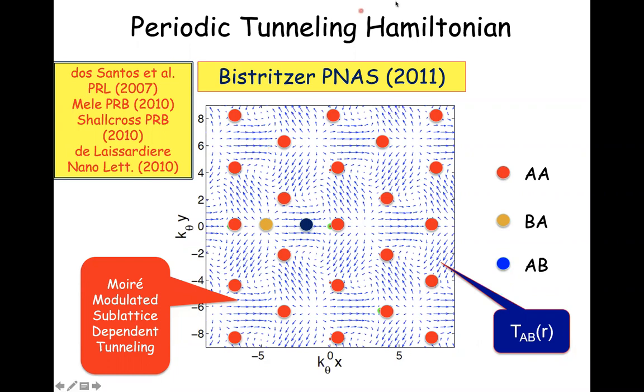So we knew, people from the graphite literature know what happens if you have 2 layers of graphite and you stack them one on top of each other. If it's directly stacked, you only hop to the same sublattice. But if there's, for example, Bernal stacking, then one sublattice of one layer can only tunnel to the other sublattice of the other layer. And so when you have a Moiré pattern, this interlayer tunneling amplitude slowly varies as a function of position. I'm plotting here, for example, the tunneling amplitude from the B sublattice of one layer to the A sublattice of the other layer. It's a complex number, of course, and the main point is that it has a simple spatial structure which simply reflects the registry between the two layers, which is slowly changing in the Moiré pattern.